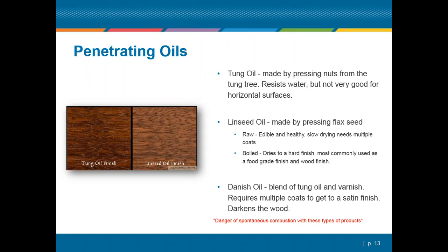If you ever use these kinds of oils, the rags need to be disposed of properly, and that would be in an airtight container with water in it, to take those rags and immerse them in the water in that airtight container so that they cannot spontaneously combust. There are story after story of people taking those rags and throwing them together and leaving them on a garage floor or whatever, and then coming back to the garage burned down.